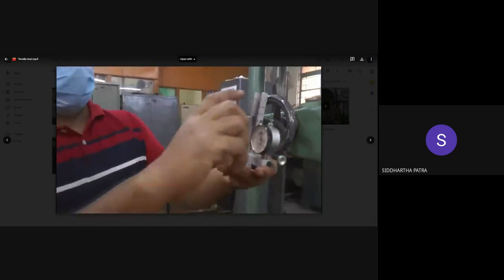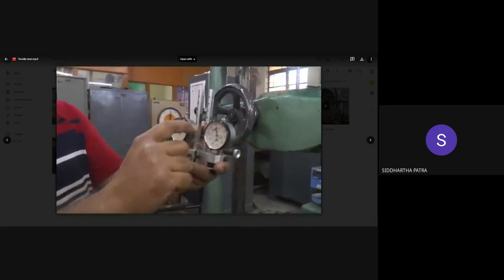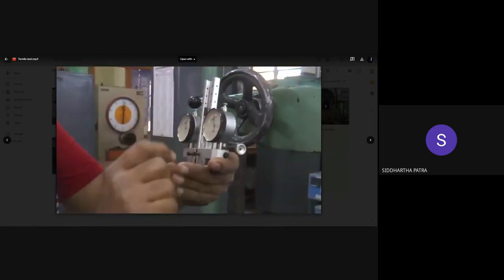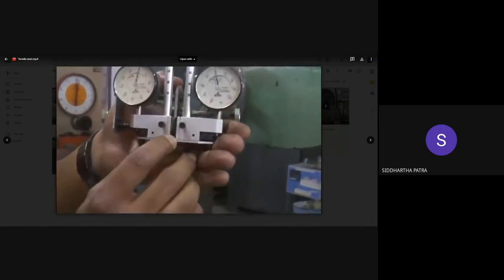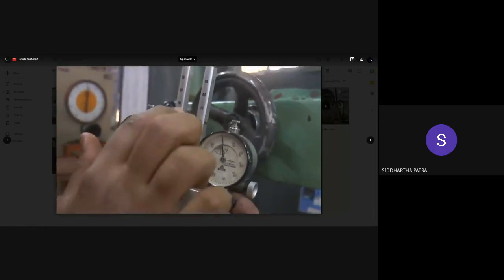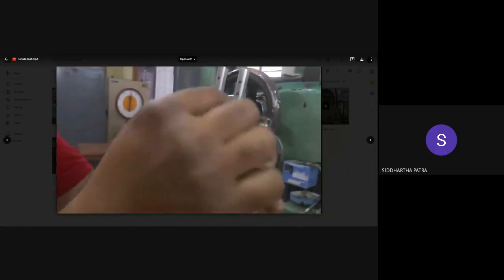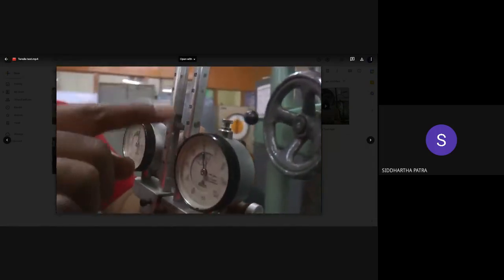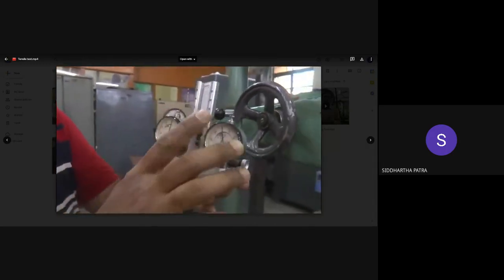These two rods are over there to ensure the gauge length. The gauge length is the gap between this knife edge and this knife edge. I hope you can see the small knife edge over here, and this knife edge over here. That gap in this case is 60 millimeters. Of course, you can move these two knife edges and make any different gauge length, but for this one, we have set it to be 60 millimeters. So 60 millimeters is our gauge length.